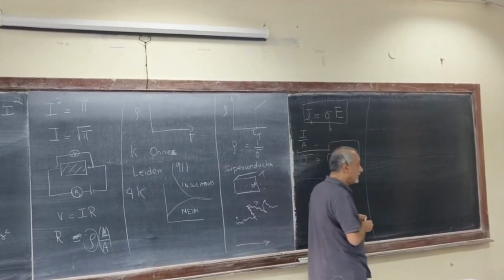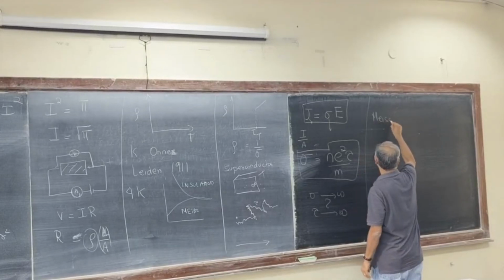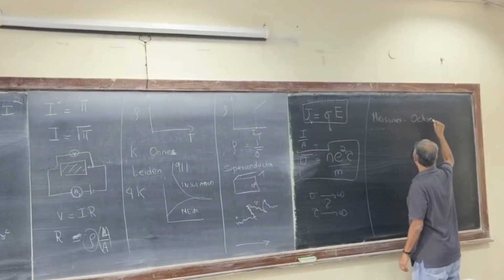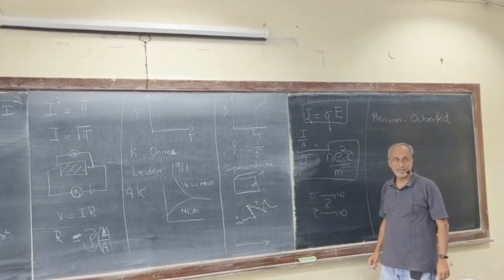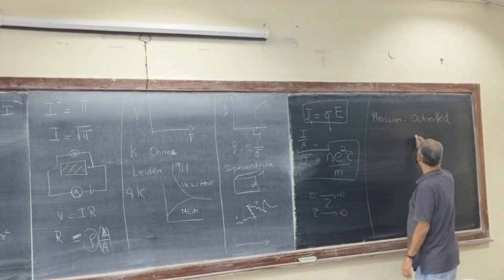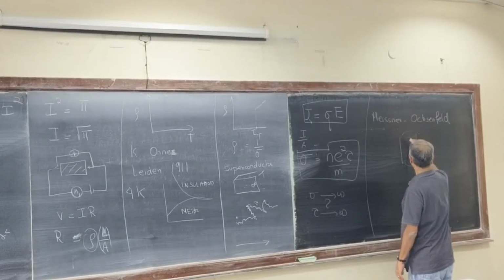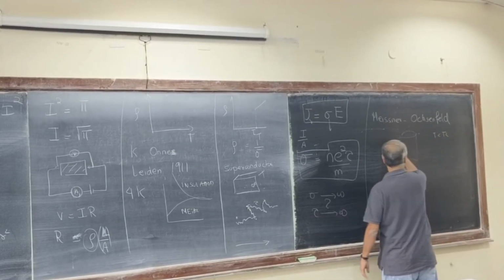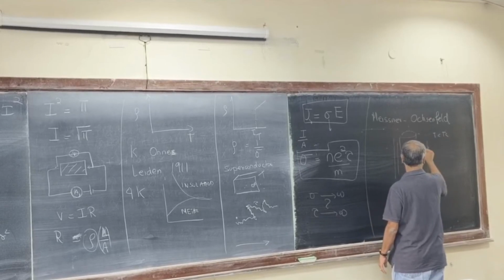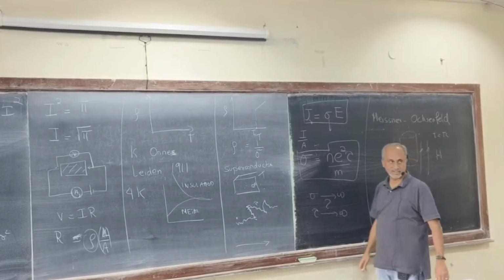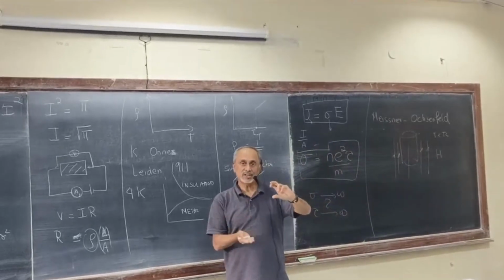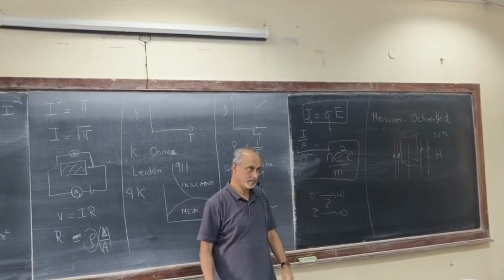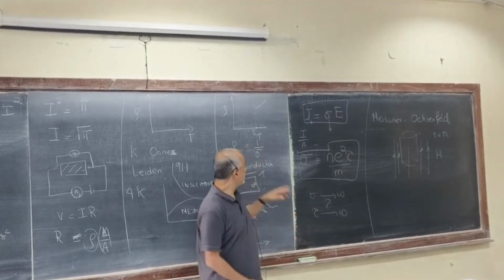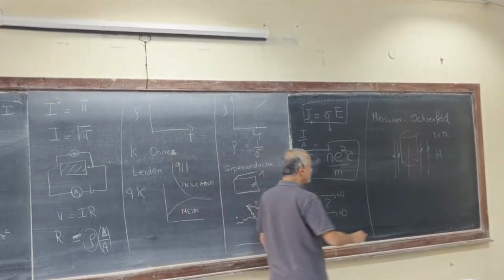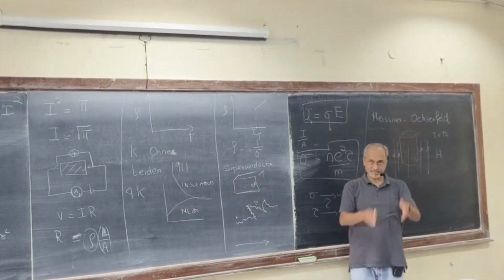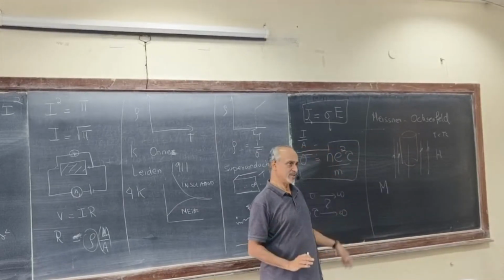Until 1933, when a gentleman called Meissner and another gentleman called Ochsenfeld figured out something interesting. And again, these were experimenters. So their experiment was to take a piece of superconductor, superconducting for field less than Hc, and look at its behavior inside the magnetic field. They took their sample, put it in the magnetic field, and then cooled it down. Rather than just measuring the resistivity, which is this measurement here, what they measured was the magnetization of this particular thing. Very straightforward.